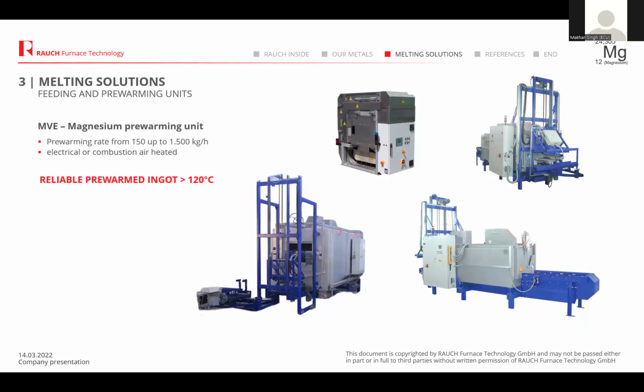Now this is a very interesting solution which we now have in mass and serial production. We ideally ask our clients, when they go for a furnace, to have a magnesium pre-warming unit plugged along with it. The ingots, before they are fed to the furnace, are already heated to between 120 and 150 degrees centigrade, so that any moisture on the surface of the ingots is gone, the time taken for melting is reduced, and your melting cycle time comes down phenomenally. So this is another product which we offer.